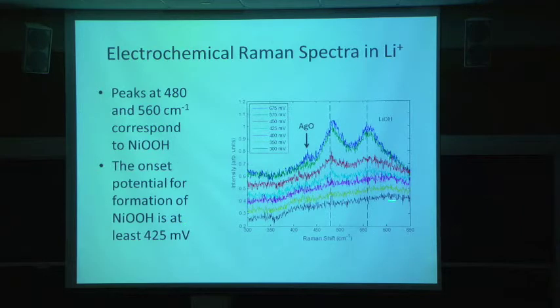Down here, we start at a very low overpotential where no oxygen evolution occurs. As we increase the potential, you start to see the formation of two peaks at these dashed lines. Right? Those peaks correspond to the nickel oxyhydroxide phase. And this is where you start to see oxygen evolution occur.